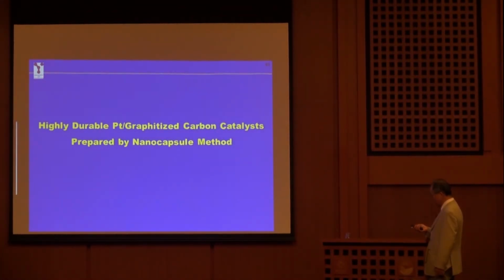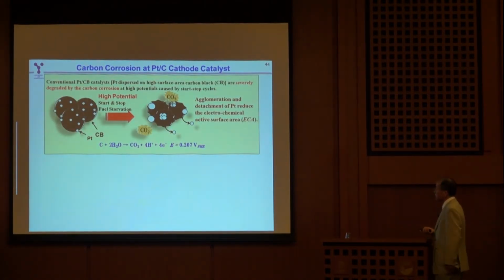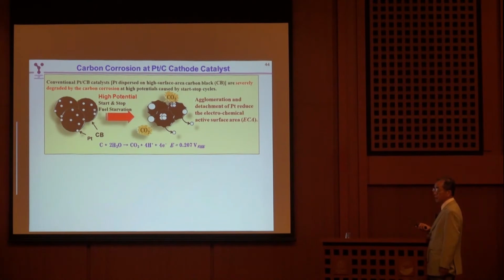And finally, I'd like to show you the benefit of the nanocapsule method catalyst from the viewpoint of durability in a practical operation condition. As you know, during start and stop cycling, the fuel cell catalyst degrades drastically because of carbon corrosion, peeling off of the supported catalyst from the carbon support, or coagulation of catalyst particles on the carbon support because of the instability of the support. So recently, people are using graphitized carbon as a support.